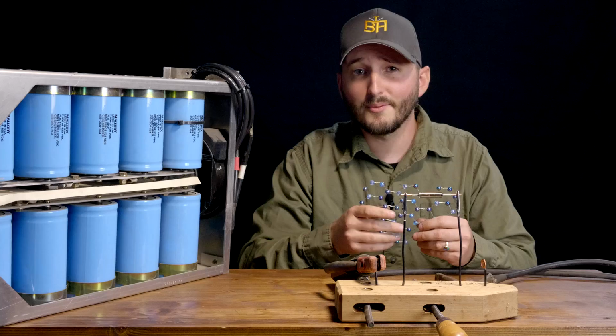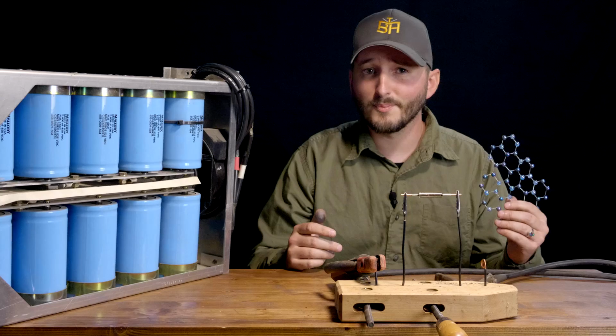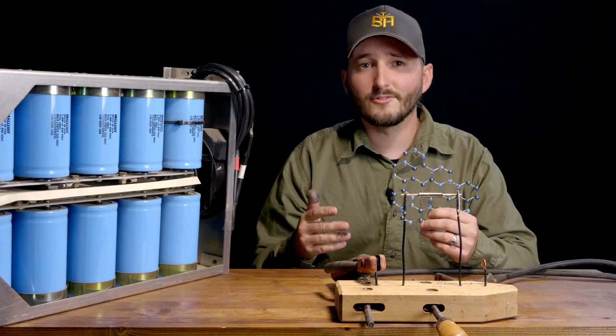A capacitor bank of this size can make about a gram of graphene with each 5 millisecond flash, of a quality that would cost hundreds of dollars per gram using earlier methods. It's been predicted before, but this, I think, is the turning point for graphene. It's simple, fast, and cheap, with a result that is suitable for both electronics and as a structural additive.